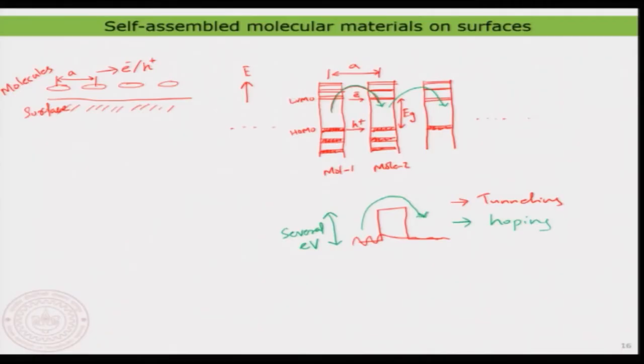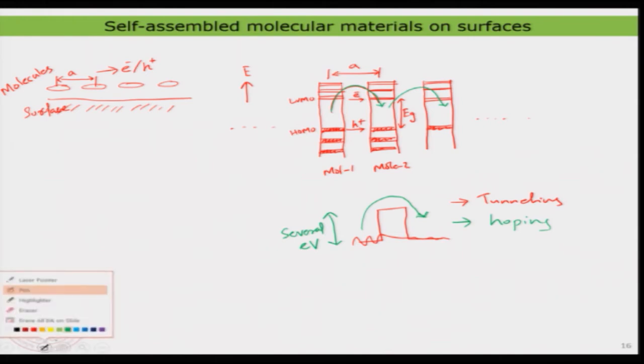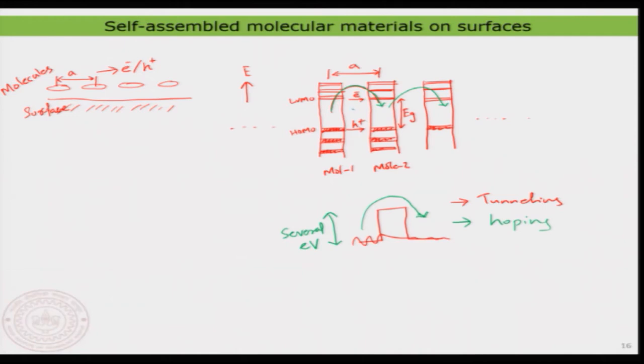Therefore, people thought we can do something else — we can try to add new states in between. If you add a new state here or there, you can clearly see the barrier decreases, and the hopping energy is also decreased. The new barrier is smaller, and when the barrier goes down, tunneling is stronger. When you have new states, hopping is more efficient because of the lower lying energy levels.